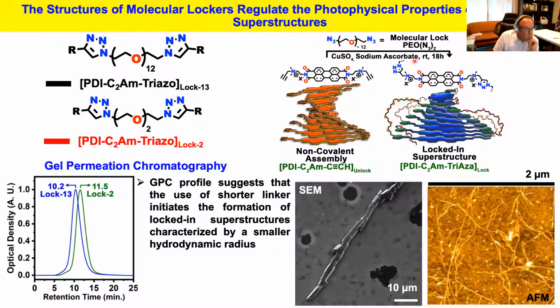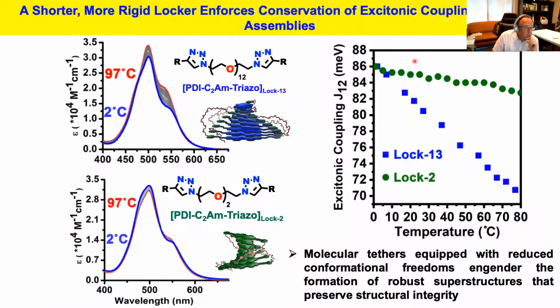But I think that one appealing aspect of using a more rigid chemical locker is what I'm going to show you now. We can start asking questions about change of excitonic coupling as a function of temperature. What you are seeing in blue dots here are the excitonic couplings as a function of temperature for the lock 13, so the longer locker. And in green here are the excitonic couplings recorded as a function of temperature for the shorter locker.